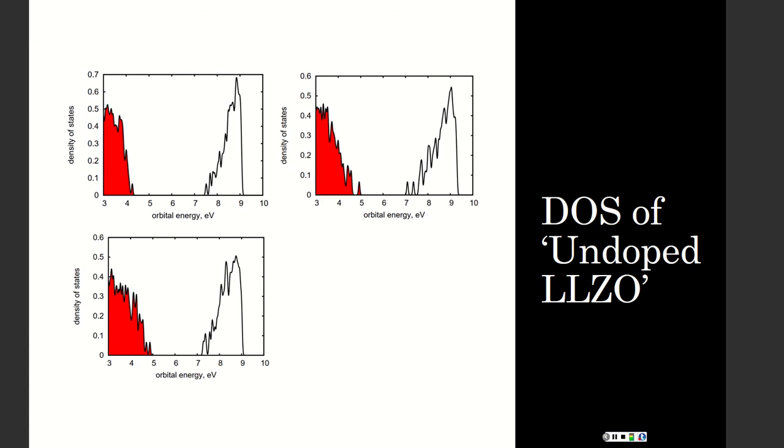So everything is the same as expected, and here in case of 1600 I can see few defect orbitals which are not present too much in the 2200 Kelvin density of state graph, and the band gap has reduced a little bit, around 0.2 to 0.5 after the heating and molecular dynamics, but everything seems normal and expected.